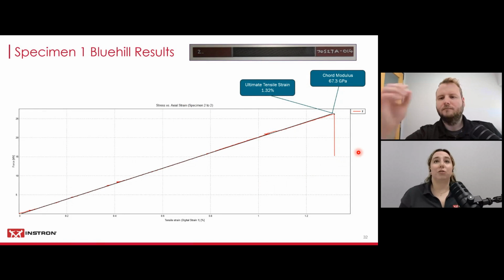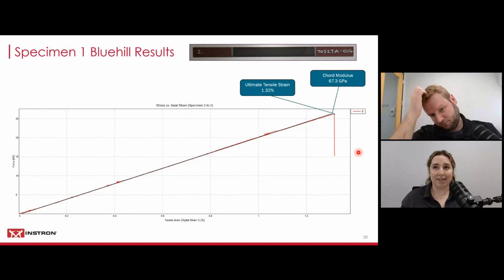Looking at the results for specimen 1, you can already see it's an immediate difference because the AVE was able to maintain tracking of the dots throughout the entirety of the test. And you'll see within that line, there's little wavy bits. The AVE is extremely accurate. It's accurate down to a micron, so it's capturing everything that's happening within your test. But really what we like here is this nice straight line showing a nice rise over run. We get an ultimate tensile strain of 1.32%, which is more correct than what we were showing with the clip-on, and a chord modulus of 67.3 gigapascals.